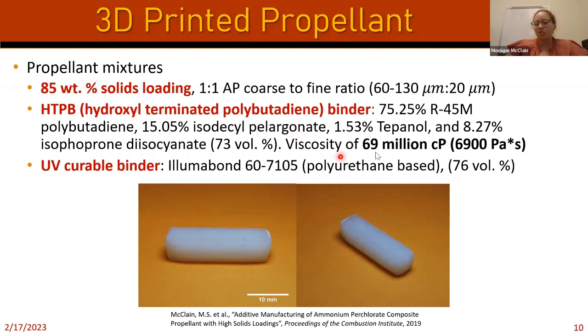So we have our mixture here and we measured its viscosity, which is relatively viscous, over time. Then we also made a separate mixture with UV curable epoxy. Again, still ammonium perchlorate, and the only thing that changed was the binder. We did this because we saw that the HTPB definitely slumps a bit, which is not ideal, and we know it takes a long time to thermally cure. So we wanted to start exploring whether we can use something that cures much faster. If you're trying to 3D print a complex structure, it's not to your benefit to have it deform while you print it. But in both cases, we achieved relatively high volume loadings. Since then, we've been able to tweak other mixtures that can be higher than this.